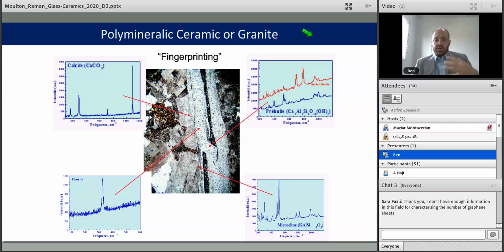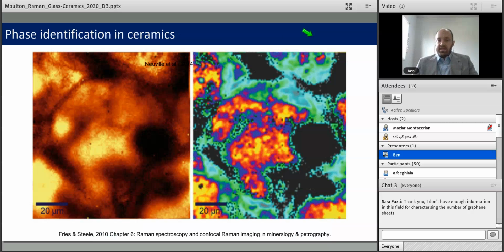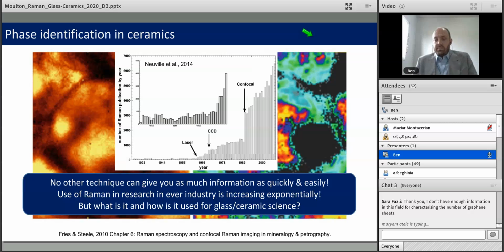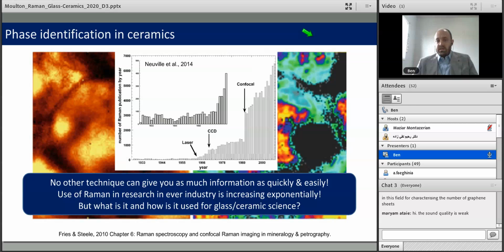We can go a step further and map where the phases are in our ceramic by using some function of the intensities, and we can measure the Raman spectra very rapidly, for very short times, over large, hundreds of microns areas in about an hour, and get all of the different phases and some degree of confidence about their chemistry from a Raman experiment. Any individual measurement, the spectra I just showed you, or this raster map that you're looking at today, can be done for a well-crystalline material in about 10 seconds. So no other technique gives you the type of information as quickly with as little processing as Raman spectroscopy, and that's why it's exploded in its use in every field of science.